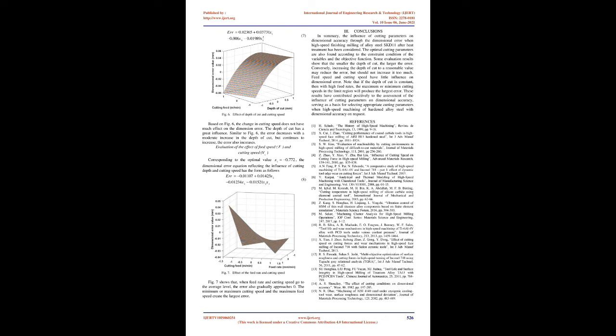Error = 0.02365 + 0.03731x1 - 0.006x3 + 0.01989x1², (7), Fig 6. Effect of depth of cut and cutting speed. Based on Fig 6, the change in cutting speed does not have much effect on the dimensional error. The depth of cut has a great influence. Similar to Fig 5, the error decreases with a moderate increase in the depth of cut, but if it continues to increase,